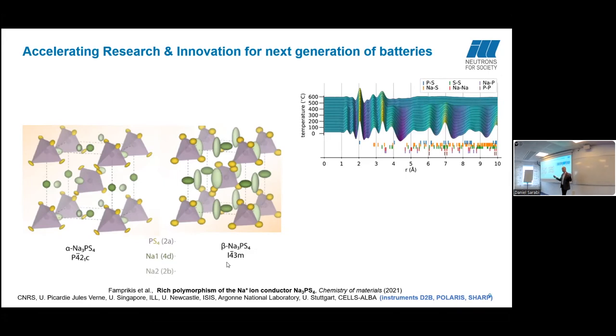But then they collected some total scattering, and total scattering is a bit like diffraction, but you measure everything and you use all of the information to generate pair distribution functions through a Fourier transform. And they did X-ray and neutron total scattering. This is a pair distribution function from one of the X-ray measurements. And these peaks represent interatomic distances. And what they found was the interatomic distances of atoms in the tetrahedra did not change across the whole transition from alpha, beta to gamma.